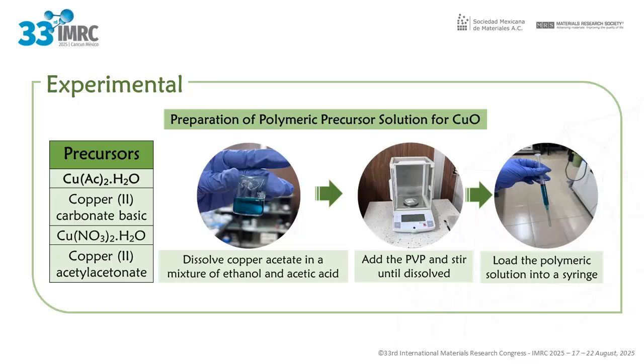For the copper oxide solution, we replicate the base of the titanium oxide solution, testing different copper precursors, as shown in the table. Only copper(II) acetate monohydrate exhibited good solubility. First, 2.5 milliliters of ethanol and 1 milliliter of acetic acid are mixed, and then 0.1 grams of copper(II) acetate monohydrate are added, followed by sonication to ensure complete dissolution. Next, 0.15 grams of PVP are incorporated and stirred until the solution is homogeneous. Finally, the solution is loaded into the syringe.